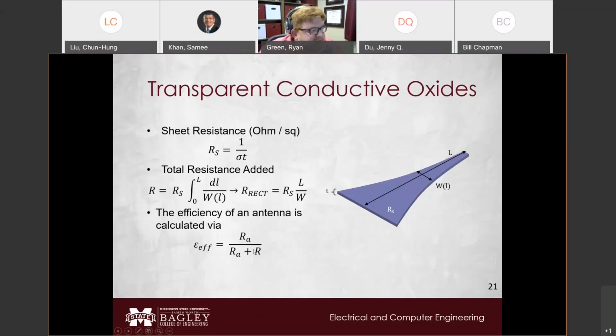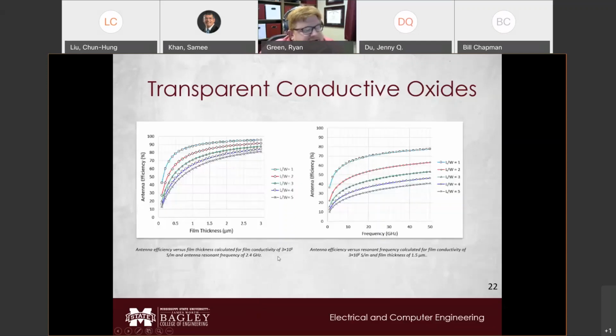Well, this added resistance now comes into play when calculating efficiency, because the efficiency of your antenna is going to be RA, which is your internal resistance, usually set to 50 or 75 ohms depending on the application, and then in your denominator, it's RA plus R. So we can see that our antenna efficiency not only changes with film thickness, but it can also change with frequency. The reason for this is that your sheet resistance can also be attributed to how thin the material is based off of your skin depth at that particular frequency of operation. The higher in frequency you go, the lower your skin depth becomes, which means electrically your thin film looks thicker and thicker with frequency, meaning you're adding in less and less parasitic resistance.